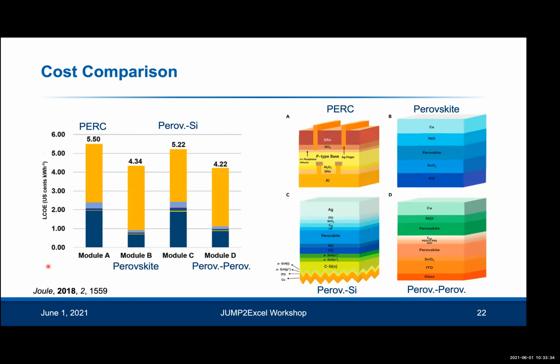And this paper here analyzed the effect on the levelized cost of energy. So if you compare perovskite silicon tandems versus a standard PERC cell, you can see that there's a reduction. But actually, it's not really a big reduction because you're still using the capital-intensive silicon bottom cell. And you can in principle make cheaper devices just by having a perovskite device by itself. There are arguments in the field about whether that's really feasible because silicon has the advantage of scale. So if you have a new technology and you leverage existing technology that already has a large deployment, then that may be a better way to have a new technology deployed at scale. So there are arguments about whether it's best to use perovskite by itself or perovskite silicon tandem.